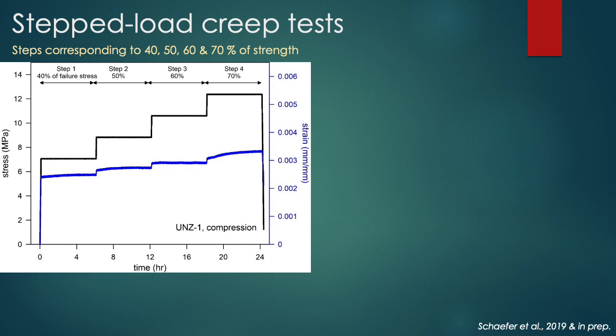As well as constant rate tests where you monitor the loading rate, you can also do mechanical tests under constant load, in which you monitor the resulting deformation rate. These load-hold or creep tests provide a valuable understanding of the response of materials under non-critical loads. In this study, we performed a series of stepped constant load tests based on the pre-measured strength, choosing 6-hour-long load-hold periods at steps of 40, 50, 60, and 70% of the material strength, both in compression and tension. In the example shown here, you can see how the strain, in blue, is relatively constant at each step until the load-hold step at 70% of the strength when the sample begins to creep.